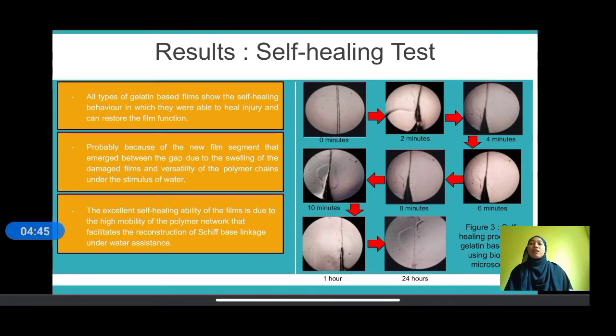Next, for the result of the self-healing test, we can say that all types of gelatin-based film show self-healing behavior, in which they were able to heal injury and restore the film function. It is probably because of the new film segment that emerged between the gap due to the swelling of the damaged films and versatility of the polymer chain under the stimulus of water, as we can see in figure 3, the self-healing process of gelatin-based film using a biology microscope.